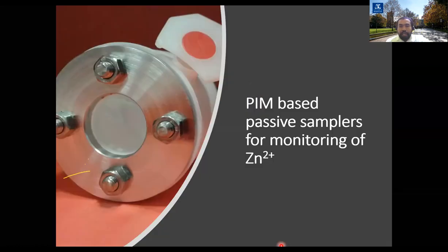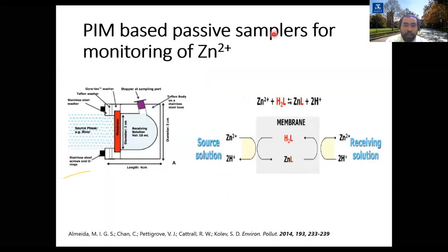The first polymer inclusion membrane-based passive sampler for monitoring of zinc is basically made of stainless steel, which has an apparatus where we can place the polymer inclusion membrane, and it has a cap where we can insert or collect the receiving solution. And this slide shows a schematic diagram of the passive sampler. What we have here is the receiving solution. This is basically the cap, and this is where the membrane is exposed to the source solution when we expose our passive sampling device to our water system. And on the right side here is the mechanism of how the target analyte, in this case zinc, is accumulated by our passive sampling device.